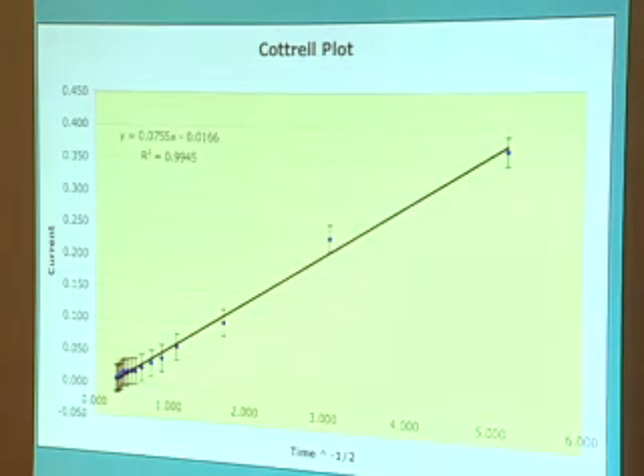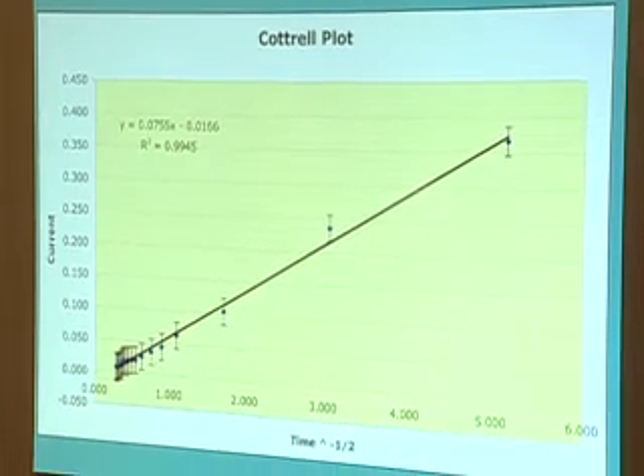So we have to go out much more than the 10 or 12 milliseconds I'm showing you there to see that it is, in fact, going to get back to the axis. And because it's not truly a plane, it probably will have a residual little current term in there. But if you take the data I've shown and throw out the first 2 or 3 milliseconds to get rid of the RC component, the non-faradaic component, and just plot that data, you can see, in fact, it does follow the Cottrell equation.